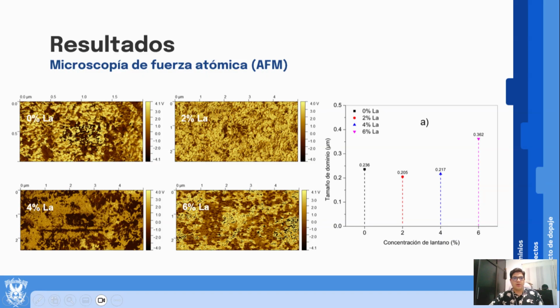The 2D and 3D topographies showed an initial roughness increase at 2% lanthanum, followed by a significant reduction at 4 and 6% lanthanum, attributed to crystallite refinement. Ferroelectric domain sizes exhibited complex behavior: smaller domains at 2% lanthanum, structural disorder, stability at 2 and 4%, and abrupt growth at 6% lanthanum, suggesting dopant-driven reorganization. These modifications in roughness and domain structure directly influence the film's ferroelectric and electronic properties for device applications.